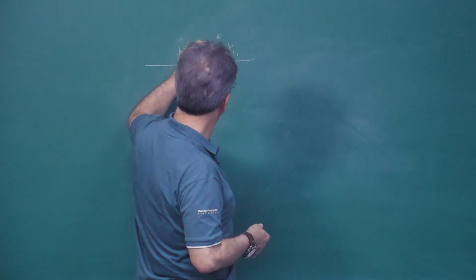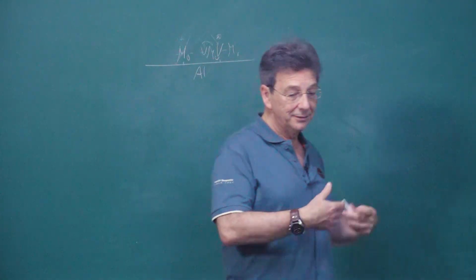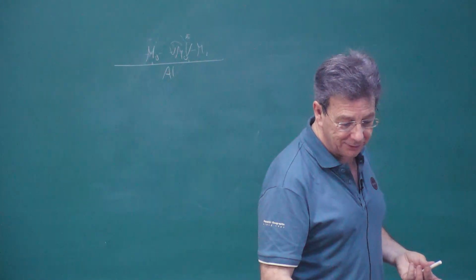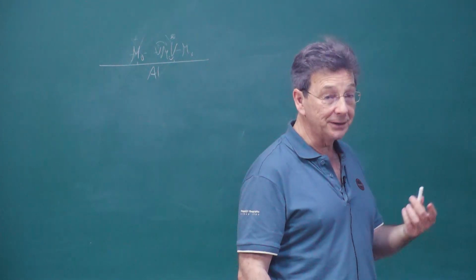But at higher coverage, you have more and more of all of them. And then in the end, they will connect and there will be an interaction between these two oxides and then you get a mixed phase. And in this case, the system has a similar performance to only vanadium, but the selectivity was better. And actually, in that case, you do have Raman bands of this mixed phase between molybdenum and vanadium that remain stable in the system.